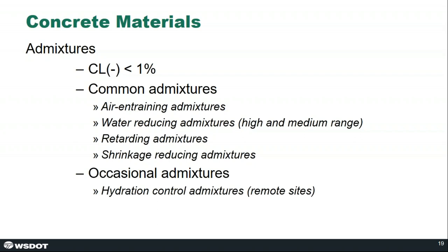Occasionally, we'll see hydration control admixtures when we've got a case where there's a really long distance from the ready mix plant to a bridge site. We have allowed the addition of these types of admixtures. They're similar to retarders, but they're chemically different. They actually stop the hydration process as opposed to just slow it down like a retarding admixture would.